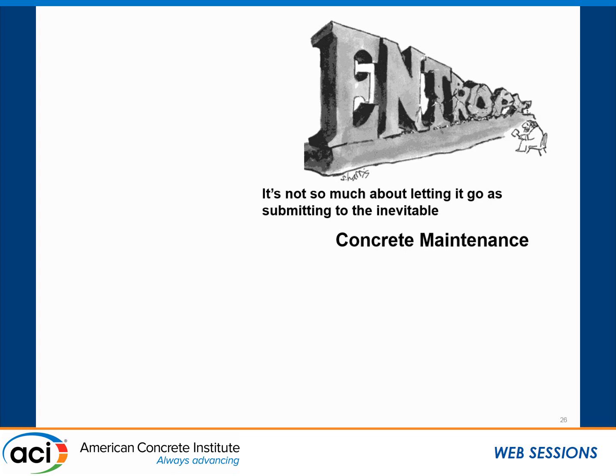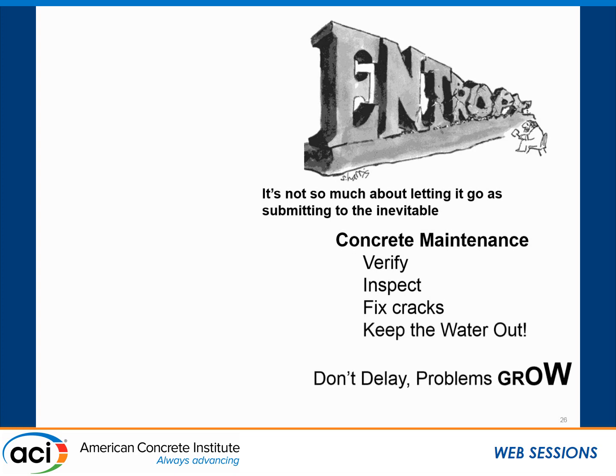Concrete maintenance. We ignore concrete once it's cast, but it really should be maintained. You buy a car, it comes with a maintenance manual. One of the most controversial things in the 562 repair code is a requirement to have a maintenance program provided. You have to verify that the repairs that you have installed are working. You have to inspect that things were done correctly. As soon as you got a crack, fix the crack. The longer the crack's there, it ain't going to get better. Yeah, you heard about autogenous healing and fancy bacteria and fungus that'll deposit stuff. Ain't there yet. Ain't ready for prime time. You got a crack, fill it with something, keep the water out. And don't delay because the problems get worse.